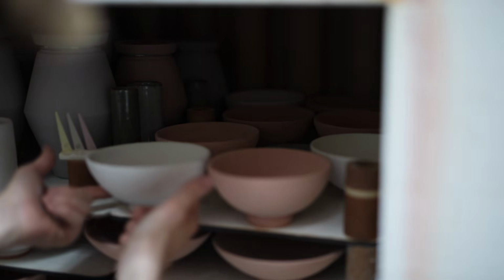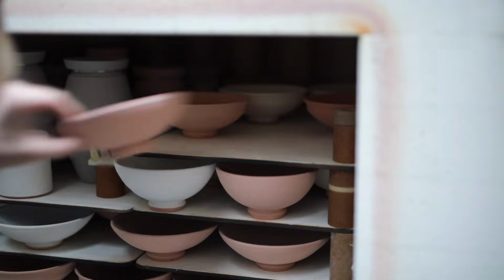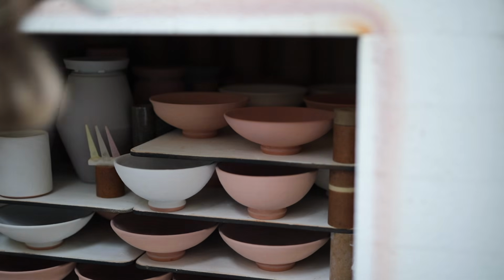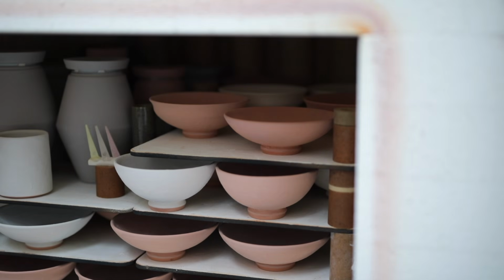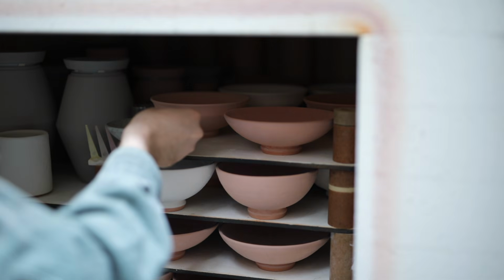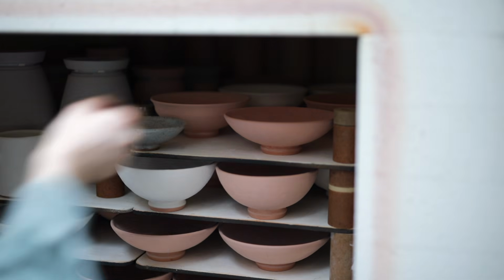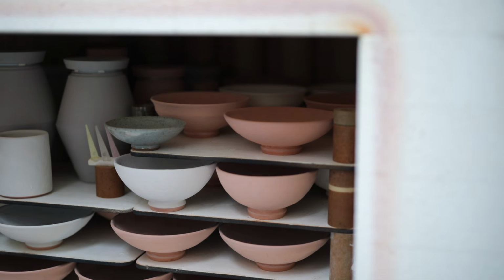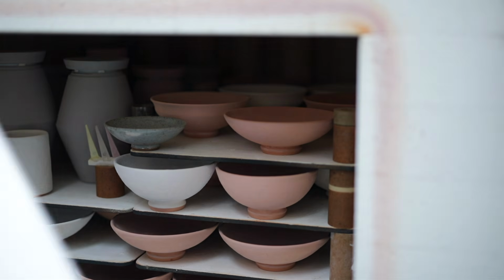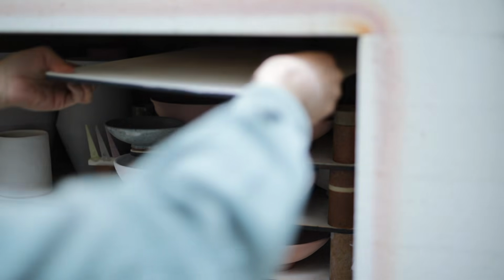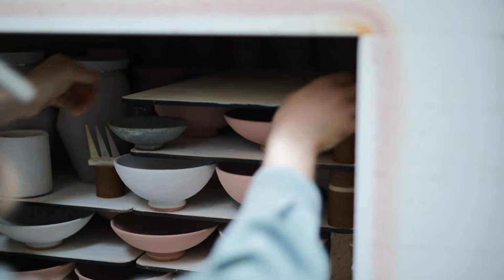You can't just fire them to a peak temperature as quickly as possible, as the glaze and clay needs time to mature. Normally I place 2 cone packs in the kiln, one at the top and one at the bottom, and as I fire the kiln I try to do so in such a way that the 2 cone packs bend over evenly, which can be tricky to do as ultimately heat rises, and it's for that reason that I take the firing quite slow towards the end, just to give the internal chamber some time to hopefully even itself out. These top kiln shelves can be very difficult to place, as I need to try my best to not knock the shelf into any of the pots, as doing so can easily damage the glazed surface.